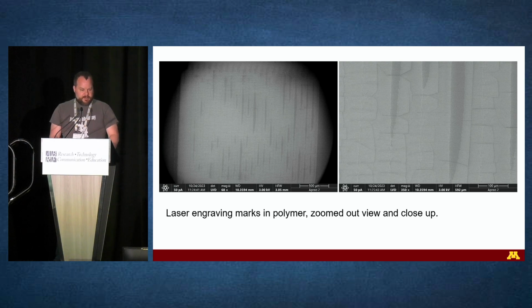In the end, we ended up using AFM to actually get a better view of what was going on, but they had all these squares lined up on this transparent polymer, and we were kind of going along and seeing if we could see the marks created by their laser, and looking at the damage of the surface of the polymer. You can see in the zoomed in view on the right, there's a lot of cracks developed from the laser as it heats up the polymer.